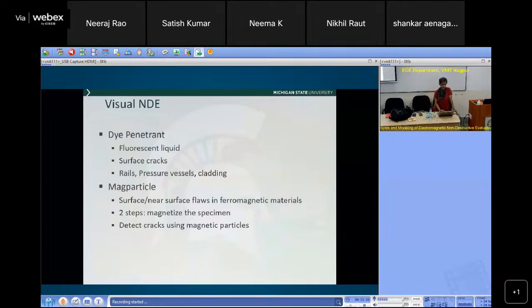Magnetic particle was a little bit of an improvement. So these liquids also have a lot of ferromagnetic particles. What you do in this is a two-step method. You first magnetize the specimen. So immediately, if you have to magnetize, the sample has to be magnetic. You cannot magnetize aluminum, right? So for aluminum, you use dye penetrant. For rail heads, you can magnetize it.